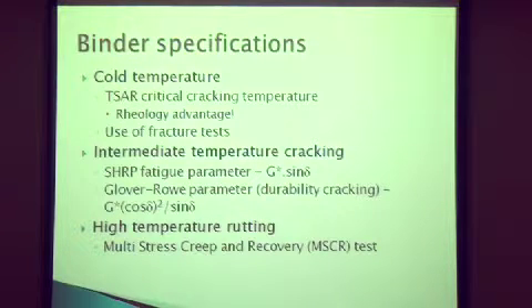What I should say here is that the rheology that's defined by the bending beam rheometer, even though you have a warmer temperature, a warmer climate here, is actually very important to you. It actually defines the stiffness in a high stiffness range very accurately. And even in a climate such as Saudi Arabia here, the importance of the rheology in the high stiffness end of the spectrum is still important for how your materials behave in terms of cracking performance. So in the US we have this cold temperature cracking, but the rheology is still important. I'm going to show a little bit more about this in a minute.